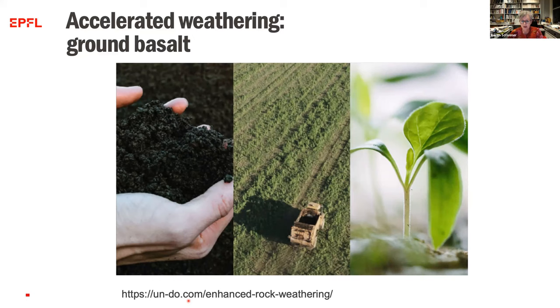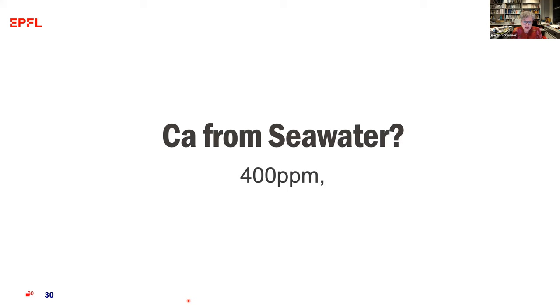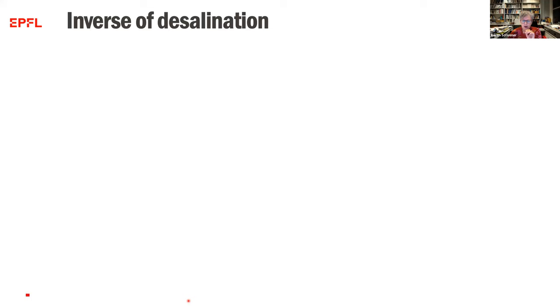And then there are people who say, well, can we take calcium from seawater? The concentration is about 400 parts per million. Nevertheless, each meter cubed of seawater contains roughly a kilogram of calcium. So could we extract that? Well, if you think about this, it's kind of the opposite of another consequence of desalination. We've got pretty good figures for desalination. It's about 3 kilowatt hours for the desalination of 1 ton of water.